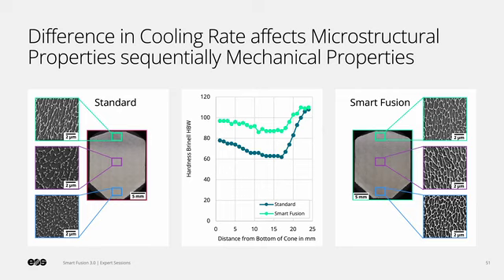Looking back at the heat accumulation demonstrator parts, let's see how the microstructure is affected here. We previously saw a high variation in radiation intensity in this part when we are not using inline laser power adjustment with Smart Fusion. That created overheated regions and differences in cooling rate. This simulates similar conditions for the material as using different preheating temperatures for the building platform. Therefore, a similar morphological change of the silicon-rich network can also be detected here.